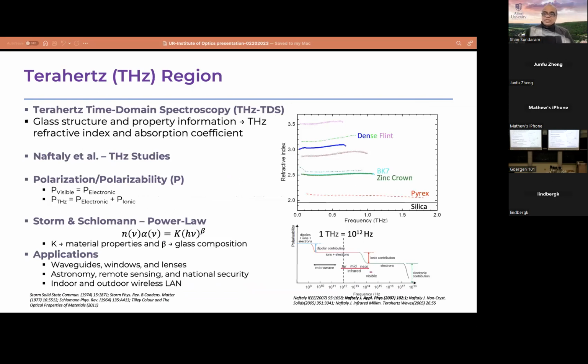There are many ways of measuring terahertz properties, quasi-optics and many, many techniques, but we have chosen terahertz time domain spectroscopy, for various reasons. Number one, the instrument is available. I could buy it using my startup about a decade ago. And also I can use the time domain spectroscopy to extract directly from the experimental data set the real and imaginary part of the optical and dielectric constant. So I can basically measure refractive index and absorption coefficient of any composition I can manage to put together. So that was our initial decision.